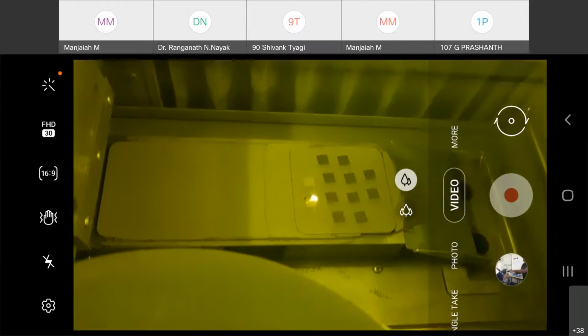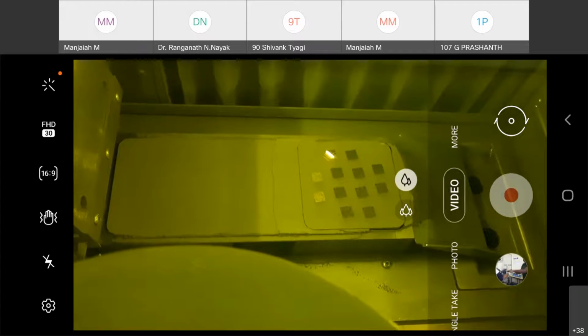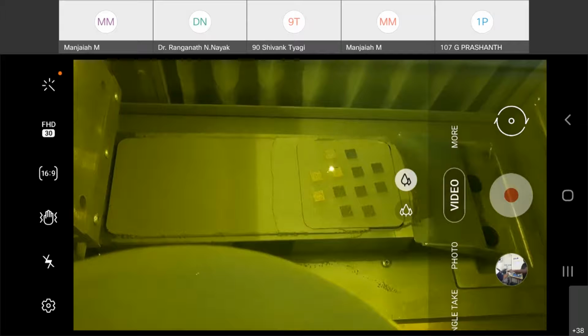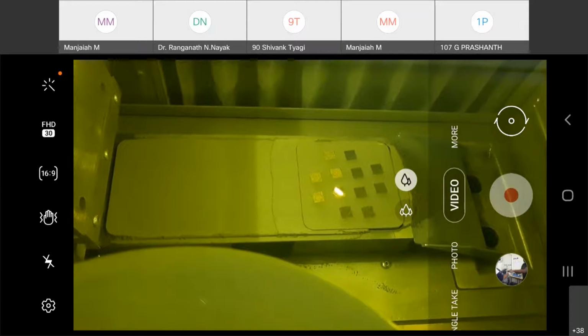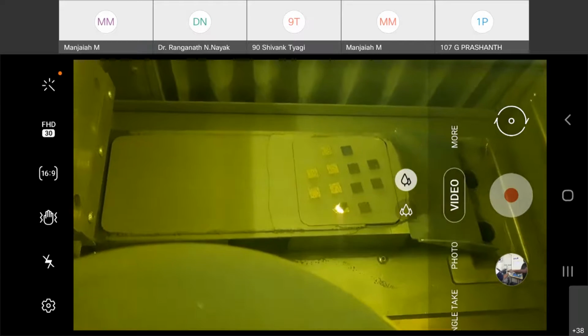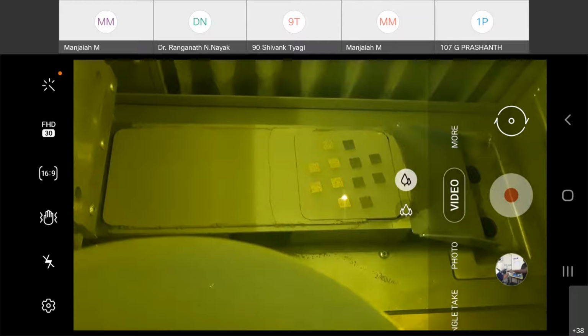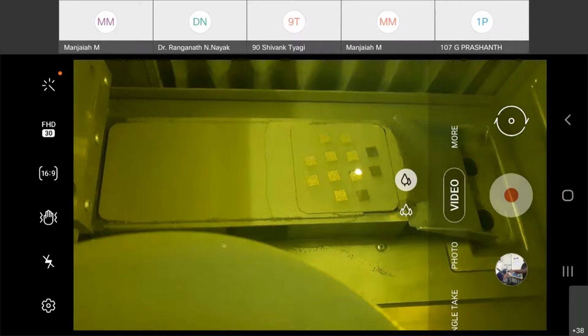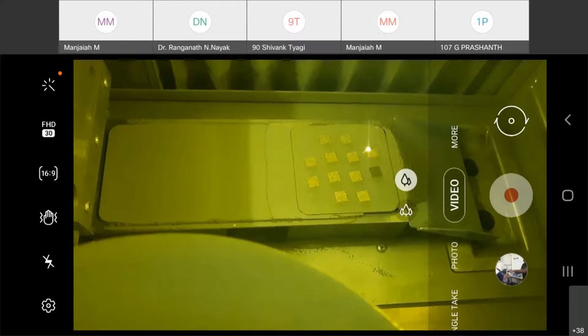Now this is the second layer, double time I am giving. So this is double sintering. So the spatter is not coming out very high during the second. Why do we focus on these spatters? These spatters are the main cause of porosity, roller obstruction and residual stress. So we need to minimize this.